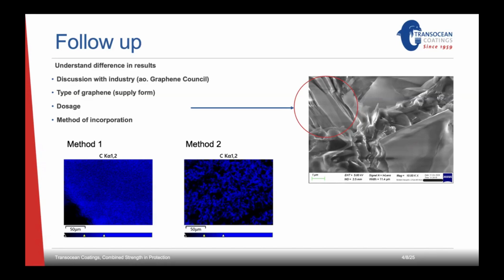The other point is the method of incorporation. While discussing with people in the field, I think it was the University of Manchester, they also communicated to us that the method of incorporating the graphene is important. What you see here are two images from an SEM picture, where on the left we have method of incorporation number 1 and on the right another one. You can clearly see that on the left, the distribution of the carbon, all the blue, is much finer than in method 2, where you see a more coarse distribution of the graphene.